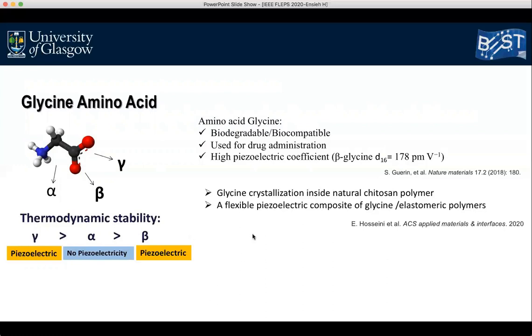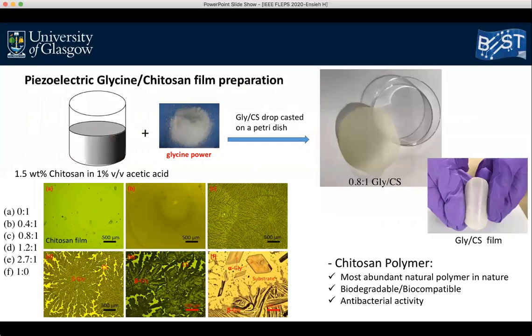So we could fabricate a flexible composite of glycine crystals and dielectric polymer by growing glycine crystals in a natural chitosan polymer. Here we chose chitosan because chitosan is the most abundant natural polymer in nature. It is biodegradable and biocompatible and has antibacterial activities.